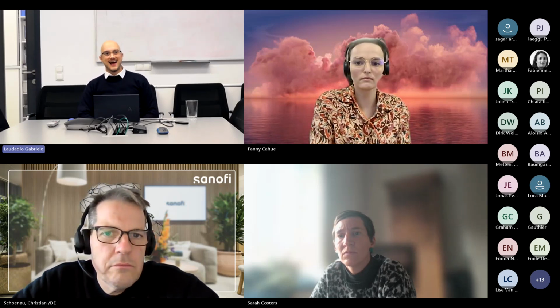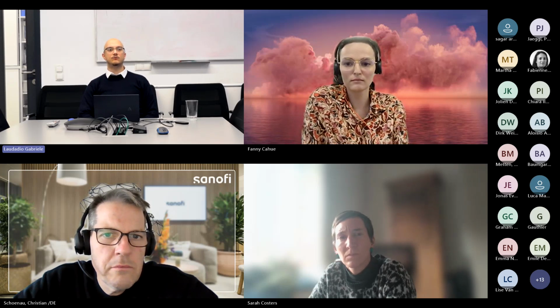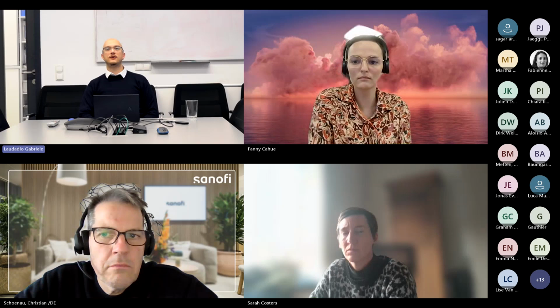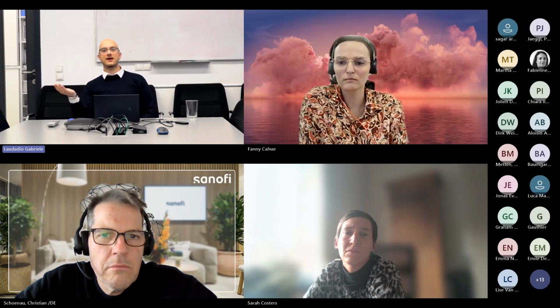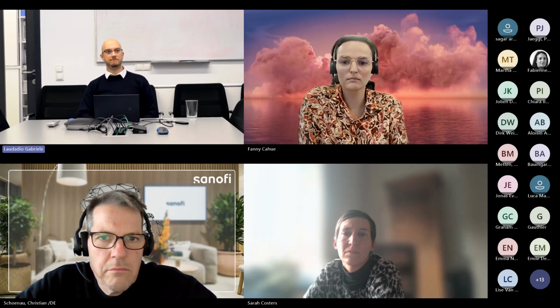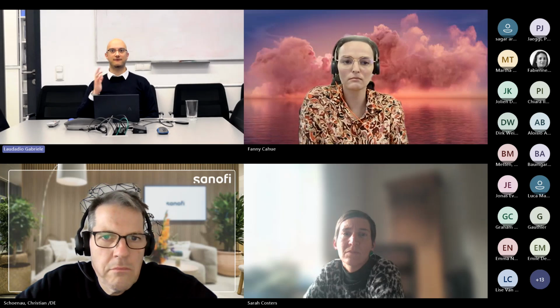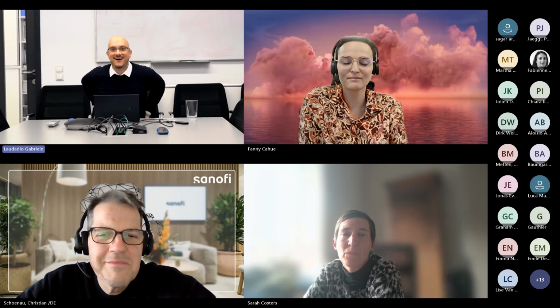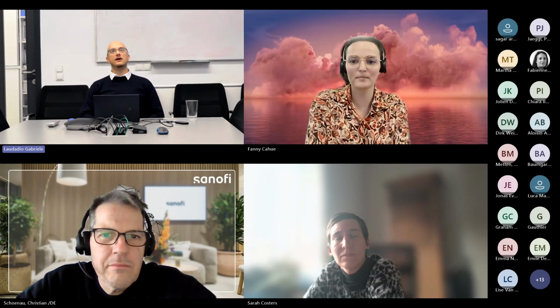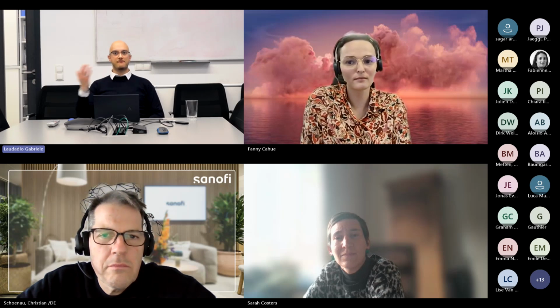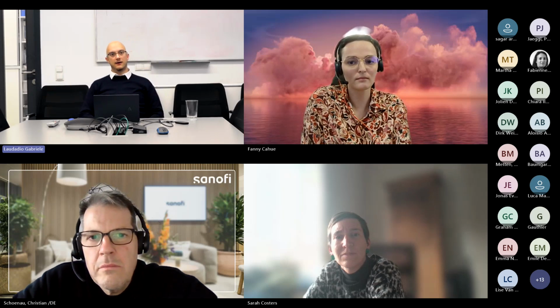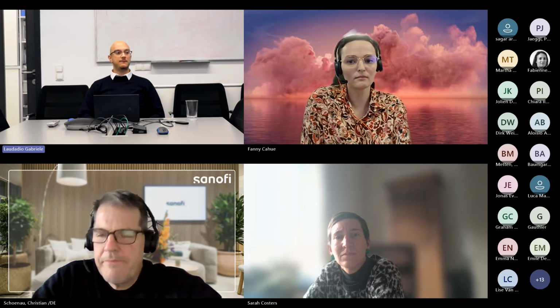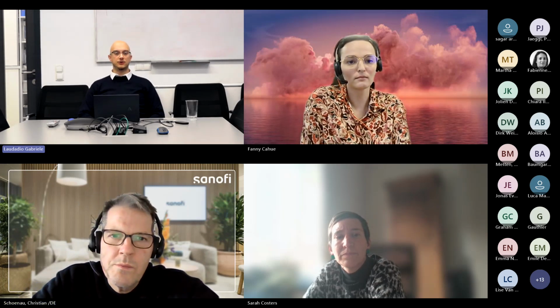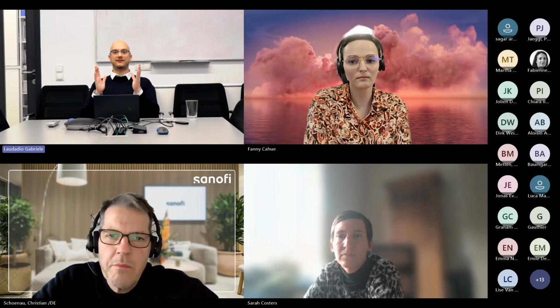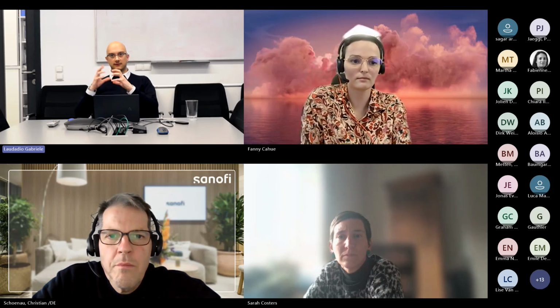But generally speaking, in terms of organic electrochemistry, by experience, I can say that the reactivity is mostly ruled by the nature of the electrode rather than the structure of the electrode. For example, if I have a metal electrode, I can expect certain reactivity. If I have a carbon-based electrode, I expect different reactivity. Generally speaking, they align relatively well, unless you have a very weird reaction. That can always be the case, but relatively simple reactions always tend to behave the same if I have a metal, regardless of whether it's a foam or a plate, and the carbon the same. The only thing that can sometimes change is the selectivity or the mass balance, but that is again more due to the dual impact of current and three-dimensionality rather than the three-dimensional structure itself of the material.